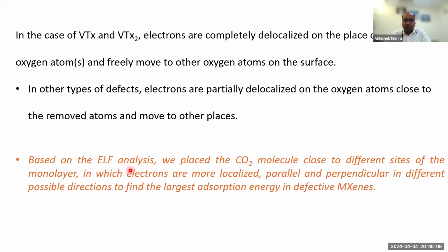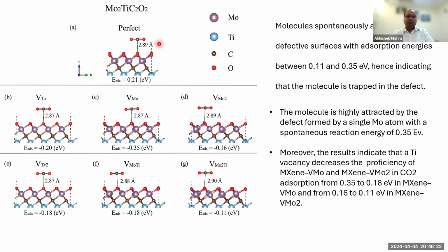So based on the ELF analysis, we place a CO2 molecule close to different sites on the monolayer and in different orientations, and we look at how CO2 is binding to the sites. These are the perfect vacancy-free cases, and these are the scenarios over the defected ones.